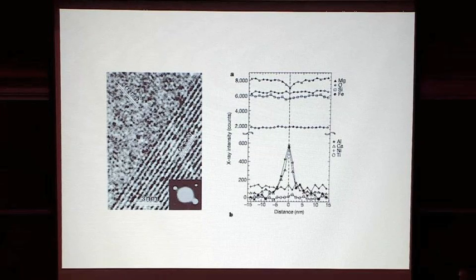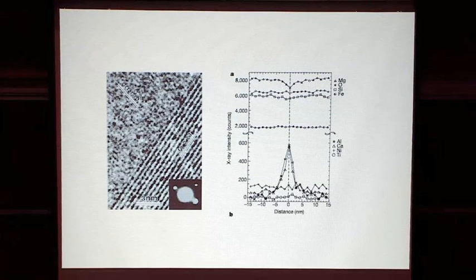But this would also mean that if we calculate or measure partitioning coefficients, we would get misleading results, because all these incompatible elements will go on the boundary, so we would be measuring or calculating in the bulk sample. Yes, but what I said before is because the total volume of grain boundaries, at least in a rock that has 100 micron size grains. If we're talking about a rock that has micron size grains, I take it back. But for a rock that has any kind of quasi-macroscopic grains, the total volume of grain boundaries in the rock is so small that even very incompatible elements are still dominated by what's stored in the lattice, except for the most extremely incompatible ones.